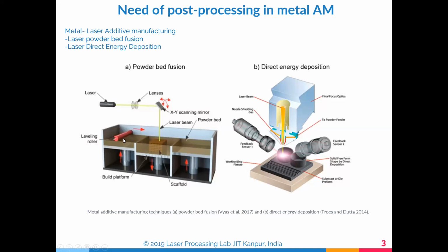So here we don't have a problem like the one we talked about with the leveling roller. Here you have one problem: the table platform can either sink down or grow up. So there you will have the same problem as here. Again, rough surface. And when you start working with metals, you should understand you will never get a very smooth layer. You will always have some amount of spatters, so you should be very careful to remove all those spatters.